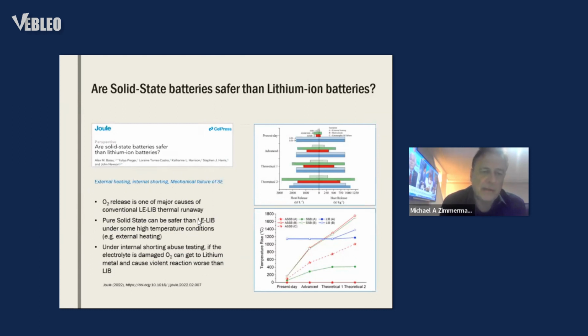a dendrite breaking through the electrolyte, because the oxygen actually caused bad reactions with the lithium metal. So one of the points here is that it's been thought that by replacing liquid electrolytes with solids, it would completely solve the safety problem. But with my work in the industry and some recent reports, it's not clear whether that's really true.